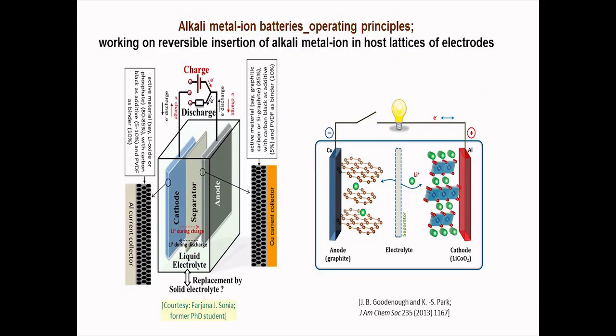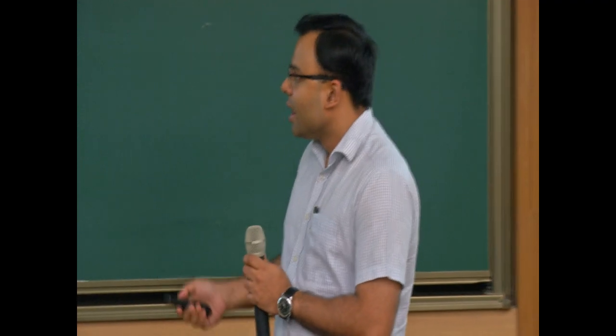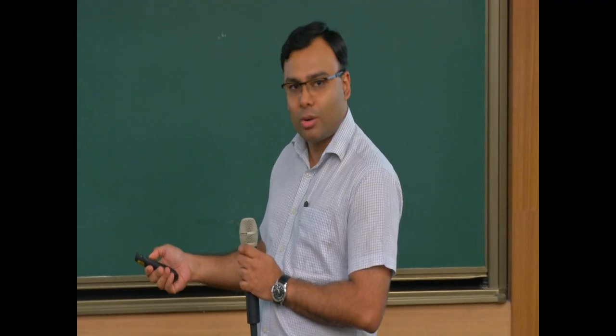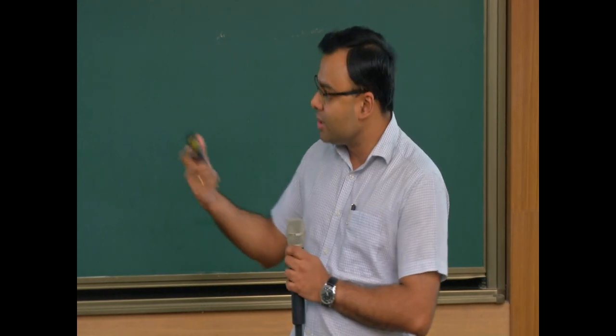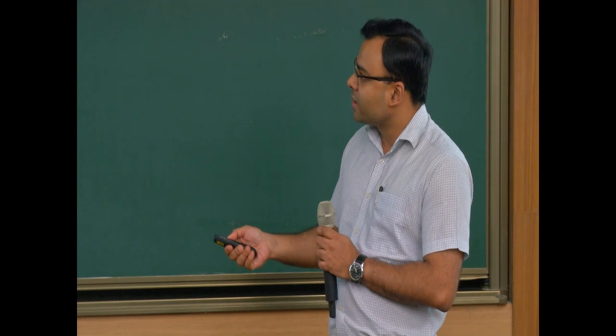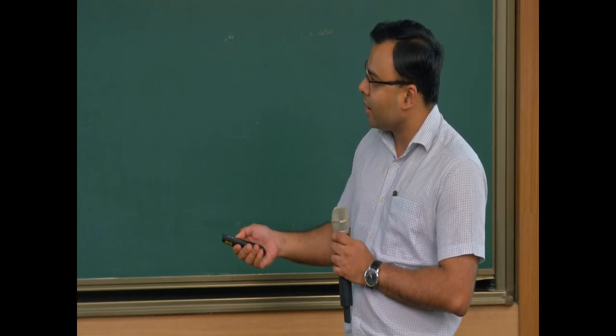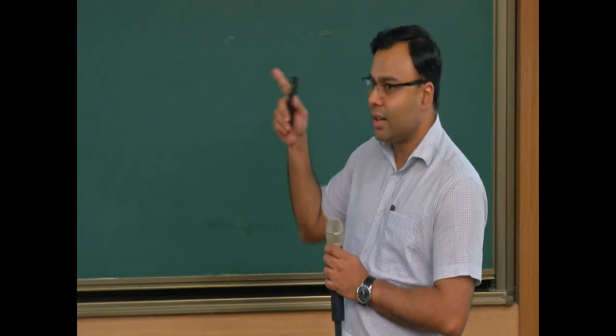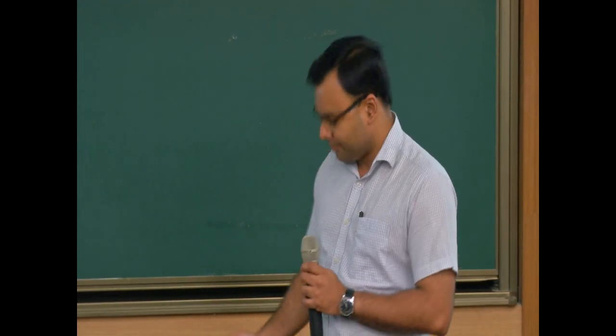So this is how the basic working principle of a lithium ion or a sodium ion battery looks like. During charging, the lithium ion would shuttle from the cathode, that is lithium cobalt oxide, to the anode, that is graphite. Any cell that is assembled is in a discharged state because the entire lithium is contained in the cathode, the lithium cobalt oxide or its variants. Then during charging, it will go to the graphitic carbon and get stored in its lattice, and again when one is using it for some application, the lithium ion will shuttle back through the electrolyte from the graphitic carbon to the lithium cobalt oxide, and one will get electrons in the external circuit to balance that.